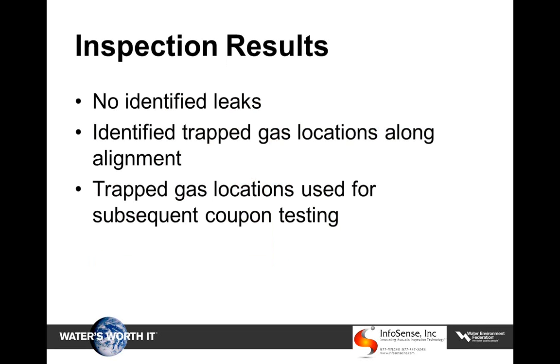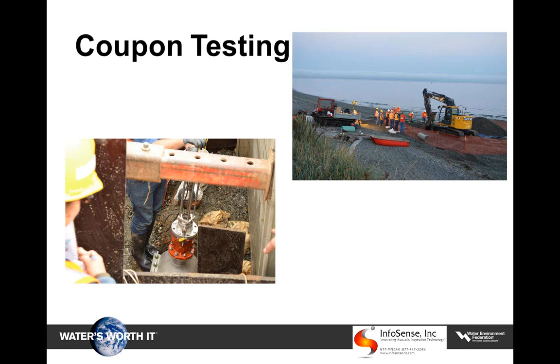As far as the inspection results of the North Beach force main inspection, there were no identified leaks. They did identify trapped gas locations along the alignment, and those trapped gas locations were used for some subsequent coupon testing. This is a fairly standard type of test, aside from the fact that it's on the beach. The coupon testing involved quite a bit of permitting from our permitting staff, who did an excellent job, and then delivered heavy equipment via barge onto the beach. We ended up taking 3 coupon samples along the alignment using standard hot tapping techniques.